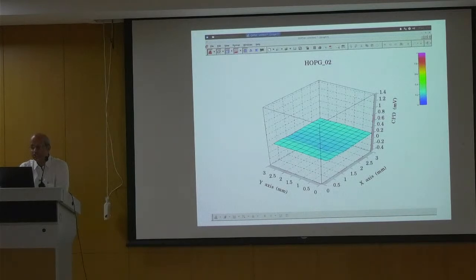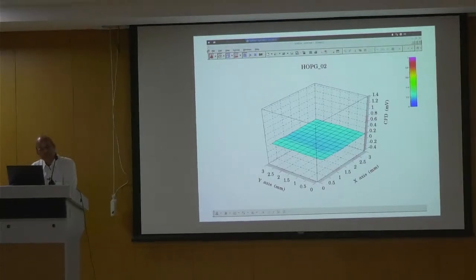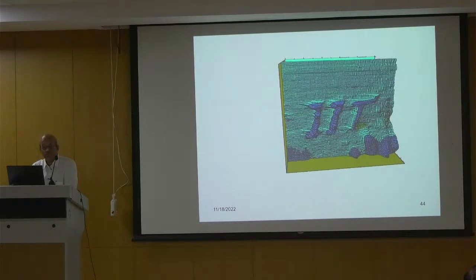The area we have scanned is about 3 mm by 3 mm. It took us almost 35 to 40 minutes to scan it. This is a 3D plot, and the z-axis gives you the contact potential difference. From the contact potential difference you can calculate the work function. The second example is that we took silicon and deposited, with a mask, the name IIT, and we scanned it. You can see wherever there is a change in work function, the mapping of the Fermi level has been done by the Kelvin probe. So it can do IIT.